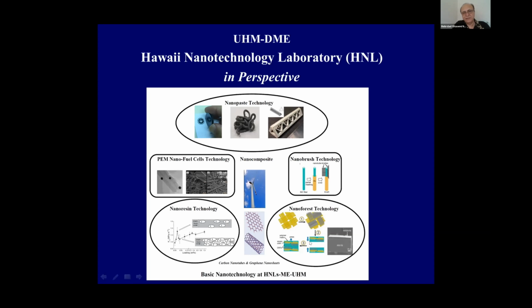And then next is a nanoforest, where we grow carbon nanotube on the surface of the fabric, then impregnate it with the resin and make laminates. This way, we improve interlaminar property, where normally is filled by matrix, but now we put nanoforest on it to improve interlaminar property, as well as make a 2D composite, a 2-dimensional composite into 3-dimensional composites. Next, we also develop world's smallest multifunctional nano brush that I briefly explained. And some of these applications in renewable energy I'll explain, including wind turbines and also polymer exchange membrane fuel cells, and that I'll explain in terms of improvement of catalyst layers and gas diffusion layers.